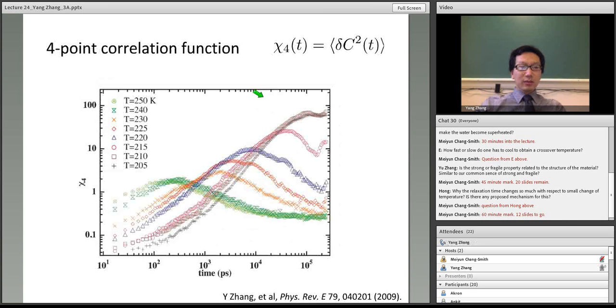More recently, people have proposed that in order to really quantify the dynamic heterogeneity, we have to go to the 4-point correlation functions, or the multi-point correlation functions. It behaves very similar to the alpha 2. So this is our simulations on water. You can see that at high temperatures, this chi4 is very small. As the temperature is lowered, the maximum of chi4 increases and increases. So this chi4 is proposed to quantify the dynamic heterogeneity in supercooled liquids.